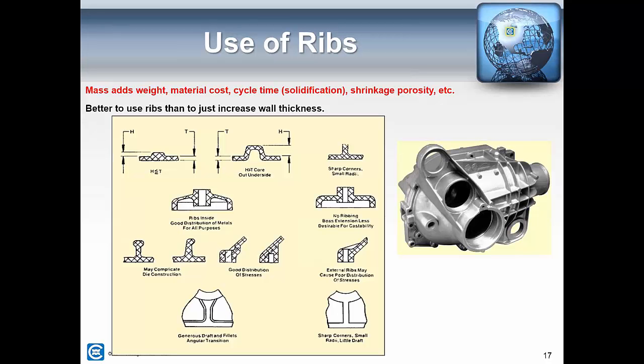Similarly, what's really telling is in the bottom views, you've got the one on the left that says generous draft and fillets, angular transition. That's the mark of a well-designed, well-thought-out casting where we're getting no sharp corners. Sharp corners tend to increase the thermal fatigue on the steel and make dies not last quite as long as they should.